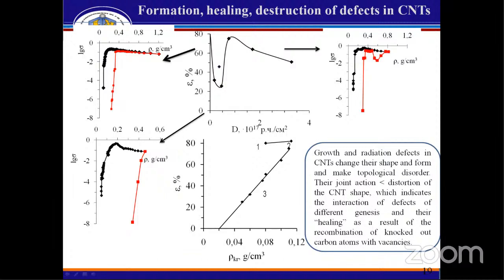Defects practically do not lead to a decrease in the elastic limit; after annealing it slightly increases, but their interaction with radiation causes a decrease in elasticity and critical density by almost 4 times as a result of an increase in the curvature of their shape due to the formation of topological defects. Growth and radiation defects in CNT change their shape and form a topological disorder. Their joint action causes more or less distortion of the CNT shape, which implies the interaction of defects of different genesis and their healing as a result of the recombination of knocked-out carbon atoms.